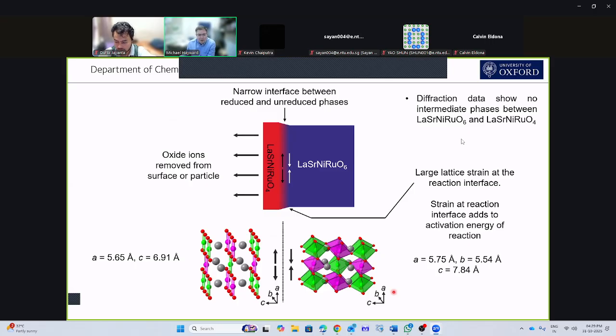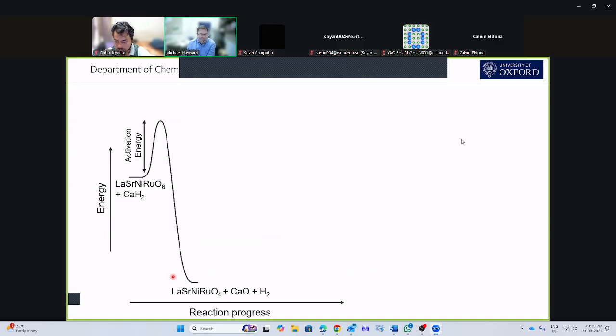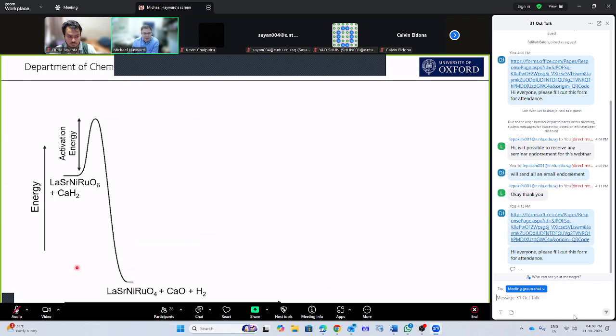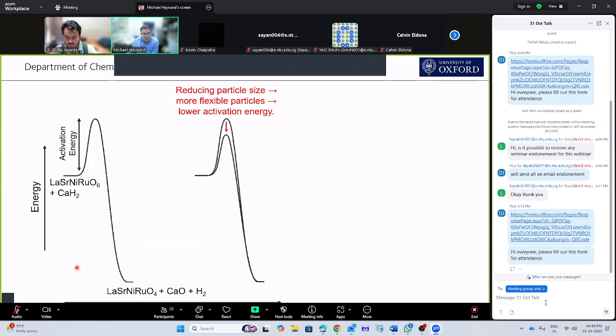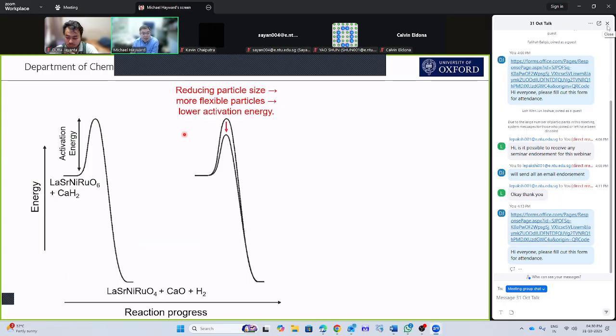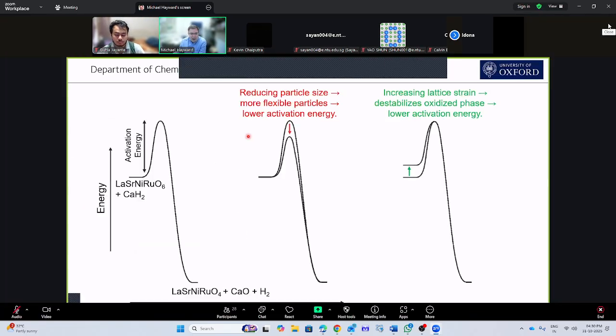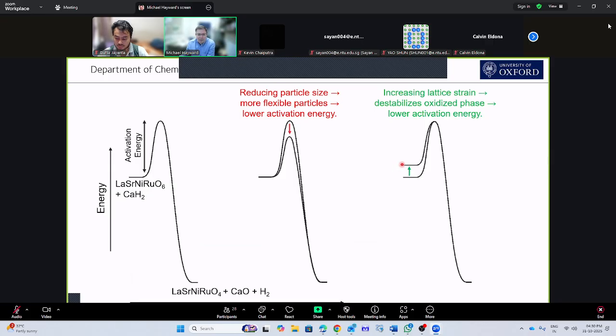So how does this affect the reactivity? Well, again, we can think about one of these reaction progress plots. And so what I'm again plotting out is the energy of our oxidized form and our reagent, and then our reduced form and our byproduct. And we need to get over this activation barrier in order to get the reaction to happen. And what we're saying is that by reducing the particle size, we make our particles more flexible. And so we can lower this activation barrier because we can mitigate against the strain that forms at the interface of the reduced and oxidized forms. And then when we add strain to the system, what we actually do is destabilize the starting material, and again, lower the activation energy of the system.